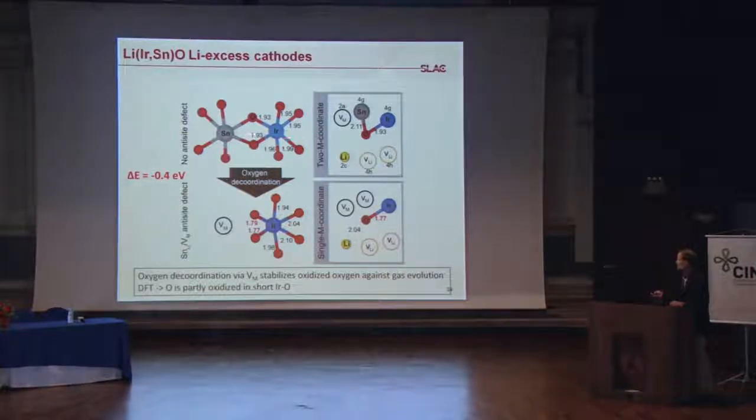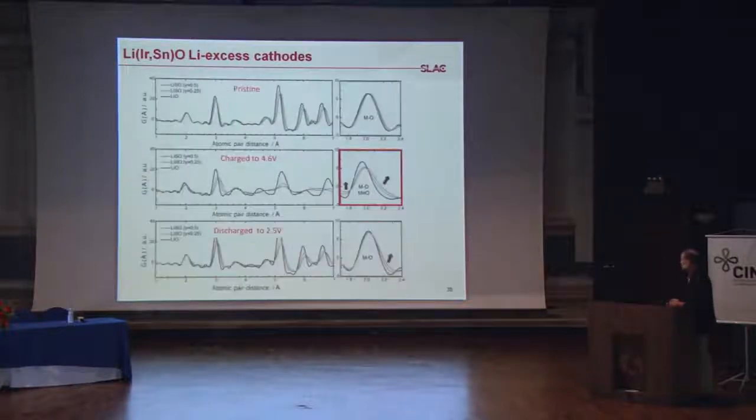So this is the local bonding arrangement in the perfect state with no defect. If this migrates to the layer beneath it, it leaves behind a vacancy. And so what happens is you see a shortening of the iridium-oxygen bonds from what had been about 2 angstroms to about 1.8 angstroms. And then a lengthening of the 2 other bonds that are on the other side and coordinated to other transition metals here. And this shows a sideways cut of the same picture.